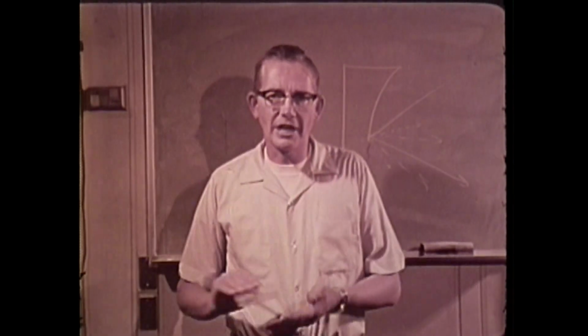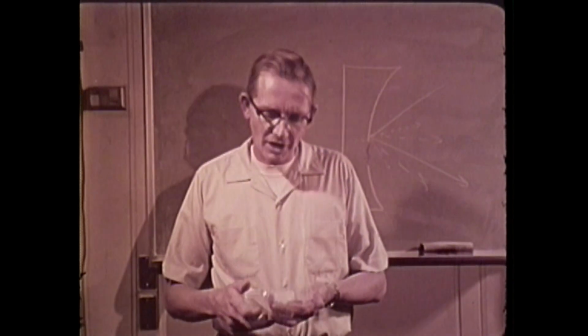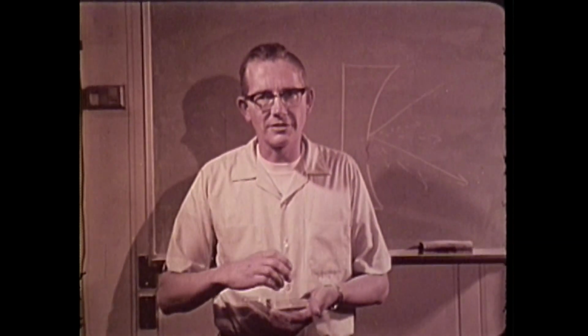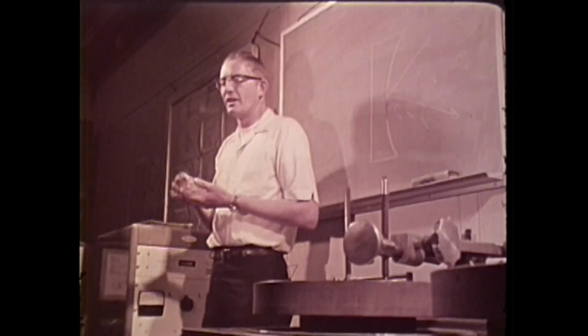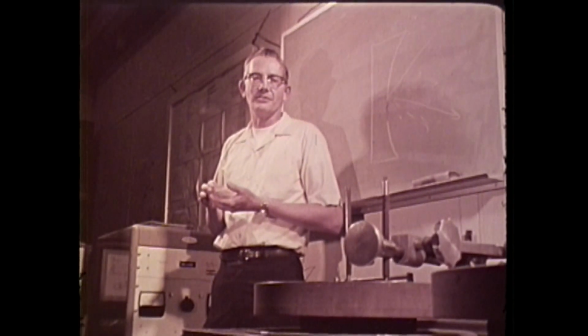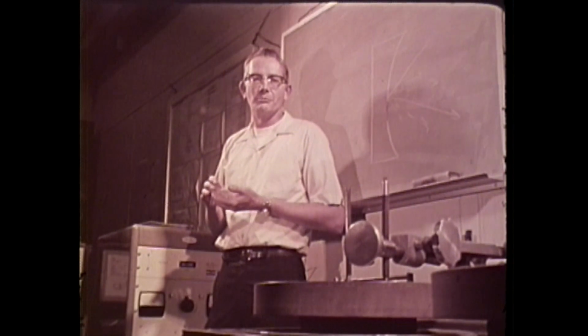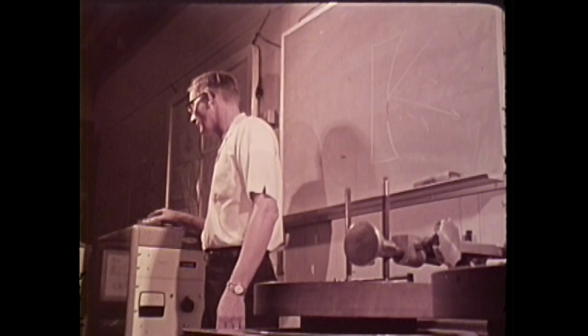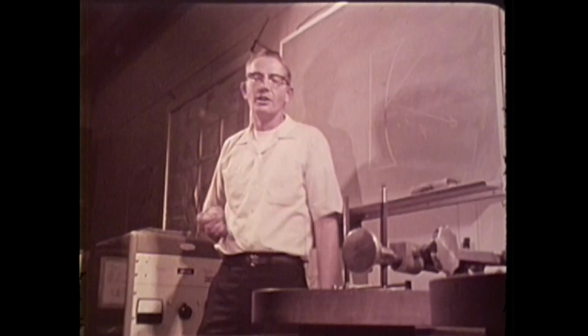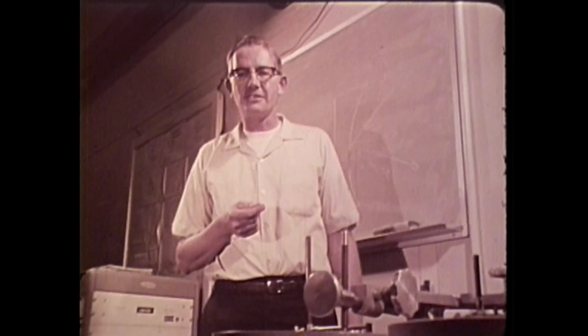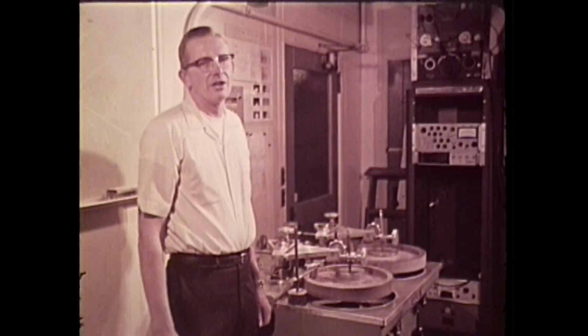To make a low scattering mirror, you've got to start with an ultra smooth substrate. A typical commercial mirror substrate has a roughness with an RMS height of about 25 angstroms. Now, 25 angstroms is extremely smooth, but we found that it's not smooth enough for critical applications. We've been able to polish to better than 7 angstroms RMS using a technique that we developed here.